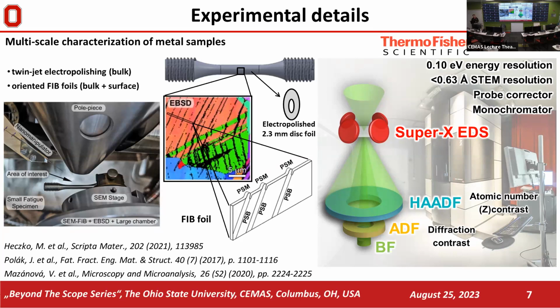In some cases, obviously, this is not the appropriate approach. So we use a workflow consisting of SEM systems and dual beam systems with focused ion beam, where we first use backscatter electrons and EBSD to select our area of interest in our metallurgical sample, and we extract an oriented and size-specific FIB foil. Why that's important, I'll mention later when I explain our approach to STEM. But we do that, for example, to make our life easier later when we are sitting in a probe-corrected system, so that our foil is already prepared, for example, without needing any tilting of the sample. We already have a low index zone axis ready, and we can start our characterization.